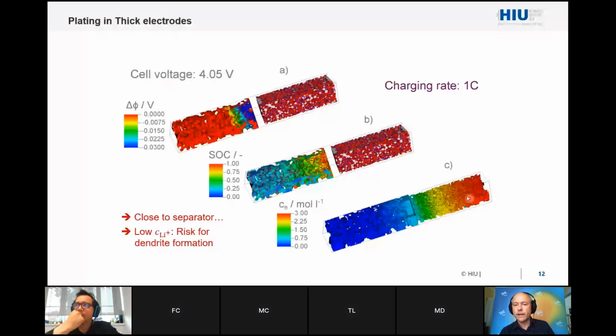Everything which is produced here in the cathode is not transported fast enough to the anode, and therefore the charging is only going to happen in a small range close to the separator. So instead of having the full capacity of a big, thick electrode, you have just 1/6 of the full capacity available, and this is immediately charged at high charging rates. Here you see that the plating is really going to happen. This is a bluish area most of the time, blue and yellow, that is close to the separator.